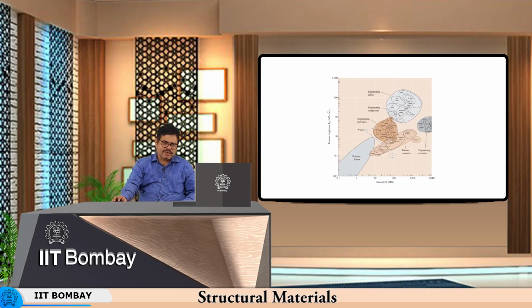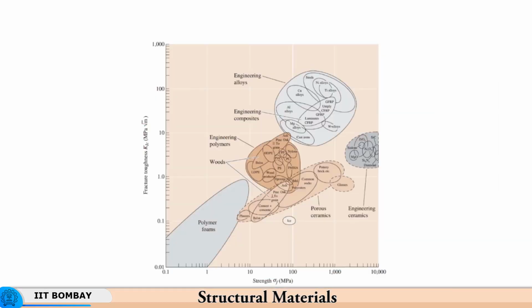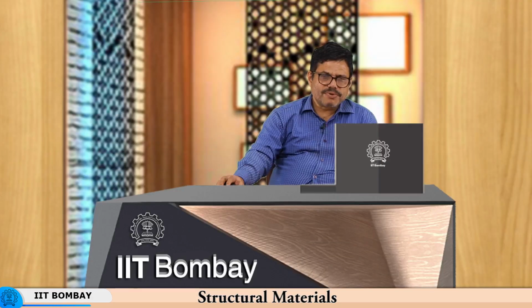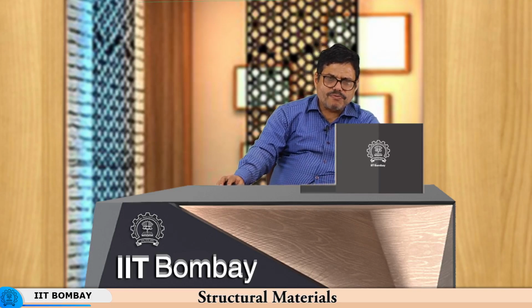Here what we see is that the different amount of fracture toughness that the material has also plays a role in fatigue, because for the fatigue crack to propagate, the toughness of the material should be sufficiently high. So, you have engineering alloys where the fatigue toughness is relatively high, and then there is medium with engineering polymers, and porous ceramics having a very poor level of fatigue toughness, and polymer foams, of course, because of inherently present defects in the form of holes. A polymer foam is essentially a fluffy entity, which means that it already has plenty of blowholes, which can be considered as defects in case of fatigue. So, with this we come to the conclusion of the topic on fatigue and fracture.